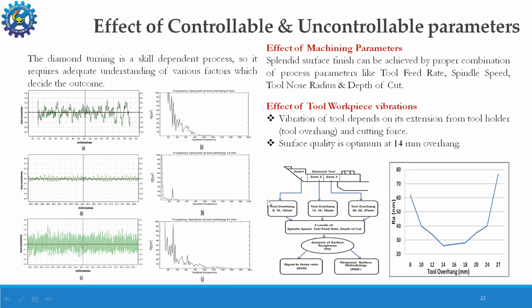So to optimize this effect of tool workpiece vibration, we have performed a series of experiments by varying the overhang from 8 mm to 27 mm depending upon the tool holder geometry as well as the logistics. So as it can be seen, when we vary the overhang from 8 mm to 14 mm, the surface roughness basically improves, like it's reducing.